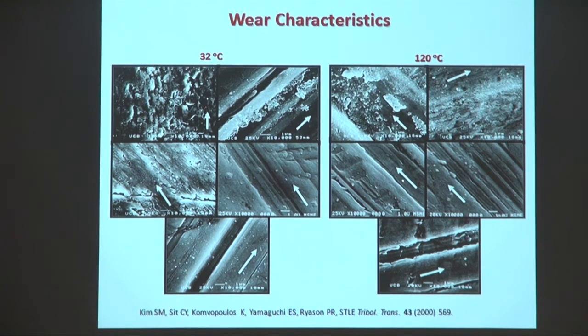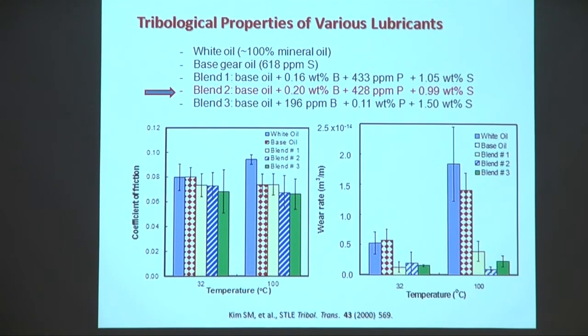Things become different when we go to the higher temperatures, where the reactivity is increased, and we can see that the film now forming is not as brittle as at the low temperature. This is the high phosphorus and boron content. So at the high temperatures, which is mainly where we need to have the protection, these two blends appear to be forming a film that prevents this excessive damage of the metal surfaces, and it doesn't have such high phosphorus or sulfur contents.